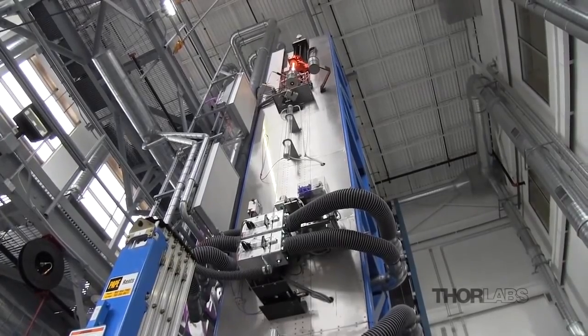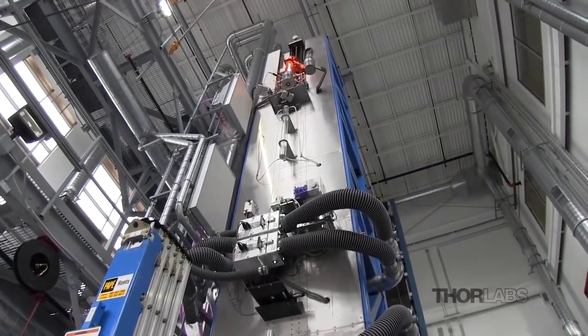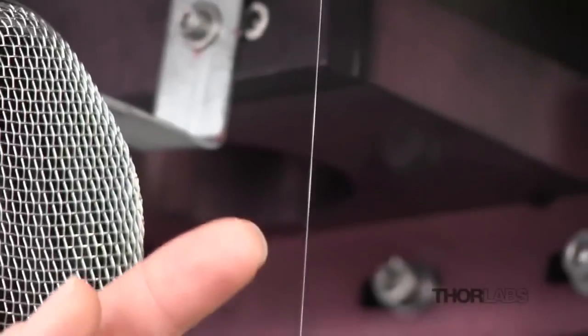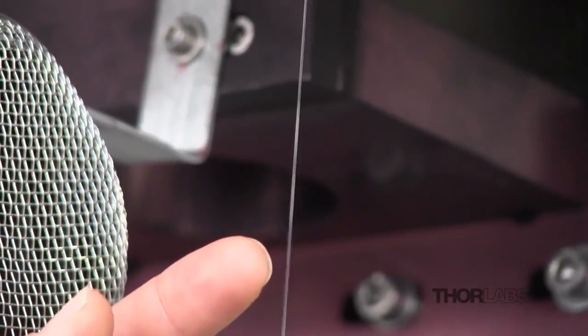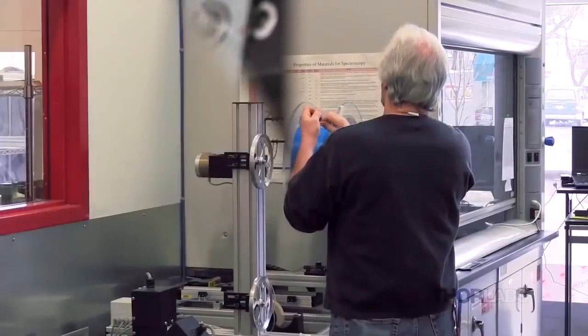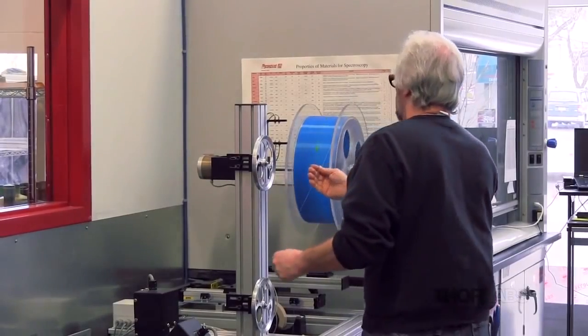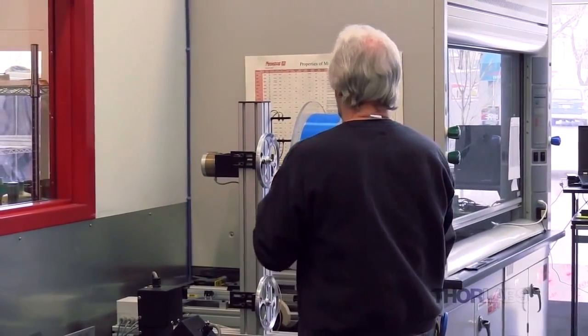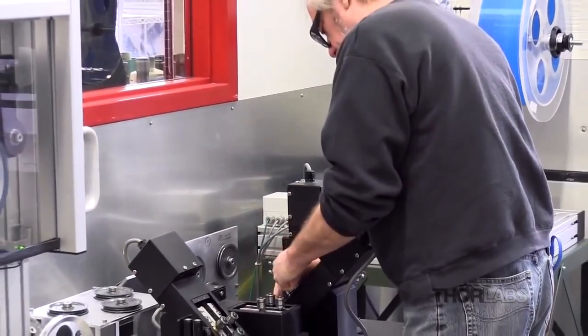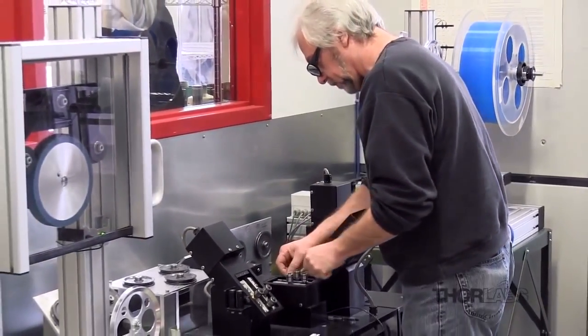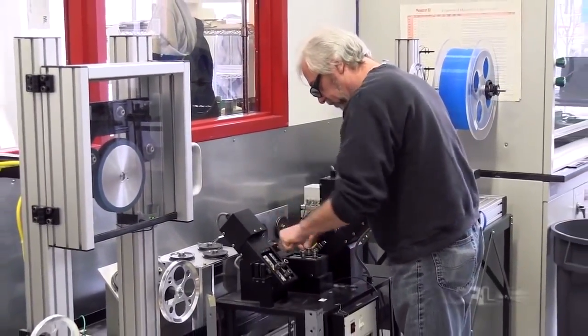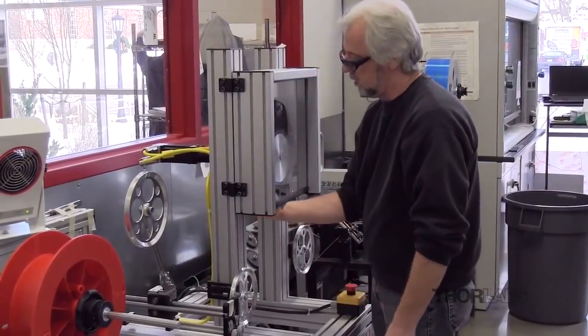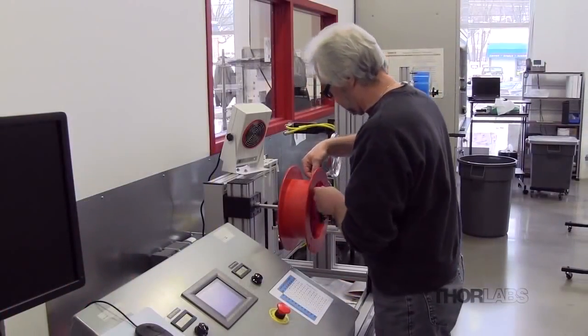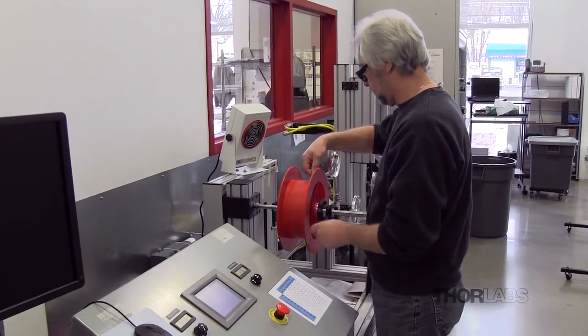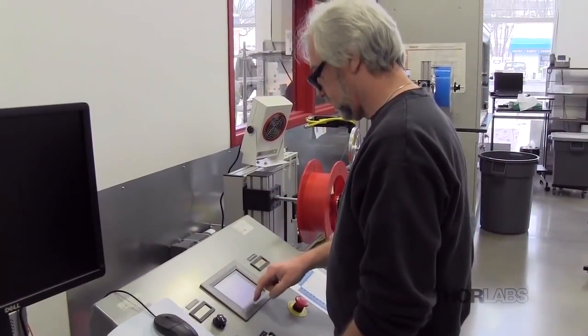This tower can produce fiber as thin as 50 microns in diameter, which is about the thickness of a human hair. The finished fiber undergoes a 4-axis proof test to measure its strength. This thin optical fiber is stronger than stainless steel of the same thickness when pulled along its length. Engineers also measure the attenuation and centration of the fiber. Any fiber that does not meet spec is not sold.